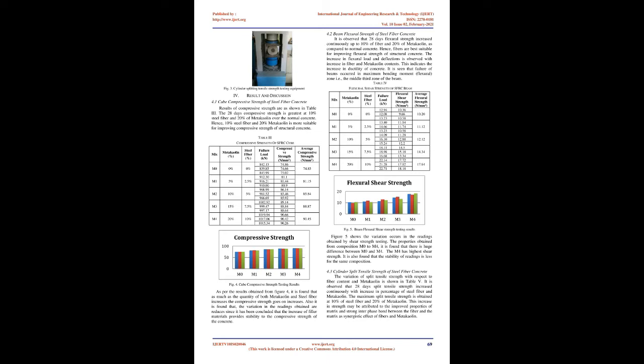Sample preparation. To ensure uniform distribution of fibers in the mix, sand and macadam were mixed firstly, and then, cement and fiber were added. After the mixtures were mixed for 30 seconds, the water and additives were added during the course of stirring. The stirring time of steel fiber reinforced concrete was 3 minutes, and the mixing process is done. The prepared mixture was put into the test mold to vibrate, and then, it was made flat. The mold was removed after 48 hours maintenance, and then specimens were cured in the standard curing room at the temperature of 20°C and relative humidity of 97%.